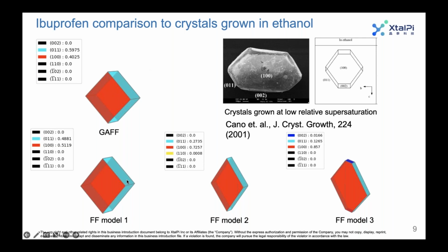We see a little bit of improvement when we use force field model 1, which takes into account only the crystal interaction energies and the thermodynamic data. Specifically, we see the 011 face becoming less of the surface area. But then we see further improvement with force field model 2, which only takes into account the solution interaction energies. We start to see thinning of this shape, which is looking more like the plates that are obtained experimentally. But we're still missing the 002 face.